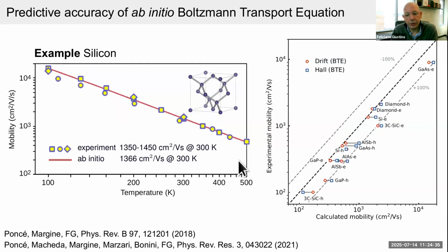So these are calculations of the carrier mobility in silicon on the left and other standard semiconductors performed from first principles. So what does that mean? We solve the so-called Boltzmann transport equation, which is a standard equation in semiconductor physics. The difference with respect to what was done 20 years ago is that all of the parameters, like the electron band structures, the phonon band structures, the electron-phonon coupling matrix elements, all of those are generated from first principles